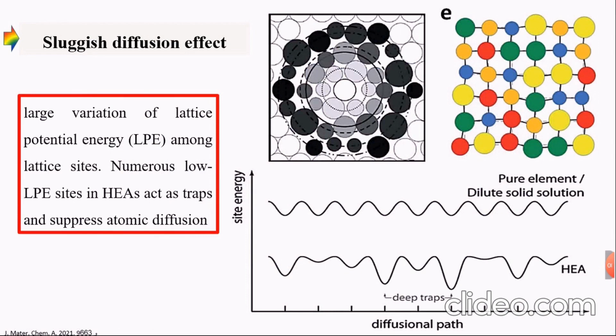Then we come to the sluggish diffusion effect. In high entropy alloys, diffusion is actually very slow. Why? Because you have a mixture of small, large, and medium atoms arranged in a funny way. So the variation of lattice potential energy among the lattice sites is large. You have numerous low lattice potential sites in high entropy alloys, which act as traps and thus suppress atomic diffusion. If you compare the dilute solid solution to the high entropy alloy, you have traps in your diffusion path. So imagine ants diffusing this way. That's why diffusion is very slow in high entropy alloys. This is called the sluggish diffusion effect.